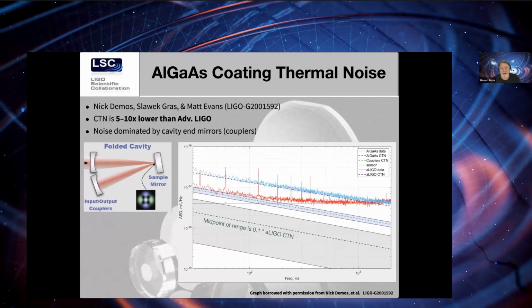Now, I've mentioned a couple of times AlGaAs's direct measurements of coating thermal noise. These are conducted at MIT. There was an experiment that was developed and is run by Matt Evans, Slava Gras, and Nick Demos. And using a thermo-optically optimized AlGaAs coating, they made the measurement that is shown here. Hopefully you can see my cursor moving around, where they made an estimate over a wide range of what the coating thermal noise probably was.